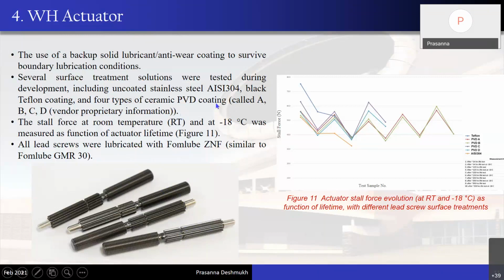We have named them ABCD because of the proprietary nature of the coating, which is developed by Smooth Motor. But we did evaluate. They provided us different motors with different shafts, and we evaluated their performance. As you can see, the four PVD-based coatings, named ABCD, survived and could give a repeatable stall force over the different intervals of the test. Whereas the Teflon coated one, as well as the stainless steel lead screw, wore out very fast and was of no use. So we selected one of these PVD coated shafts for our further progress.